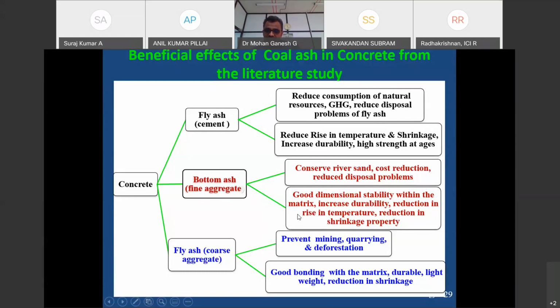Indirect benefits are good dimensional stability within the matrix. It increases the durability of the concrete, reduces the rise in temperature like fly ash, and reduces shrinkage. Fly ash aggregates in place of coarse aggregate directly prevent mining, quarrying, and deforestation. The indirect benefits are good bonding with the matrix, and it is durable, lightweight, with reduced shrinkage.